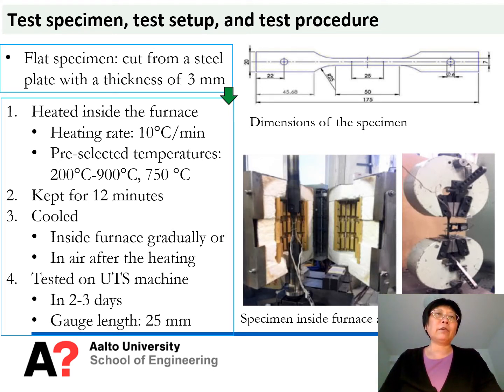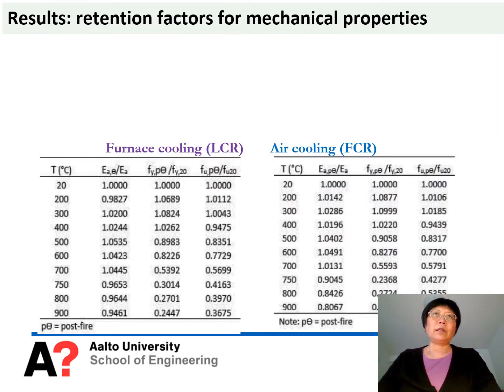And then in a couple of days, all the specimens were tested on a universal tensile test machine, and the gauge length used was 25 mm. And here are the retention factors for mechanical properties for the furnace cooling method and the air cooling method, as can be seen here. So basically the retention factor for modulus of elasticity reduced at the cooling temperature of 750.